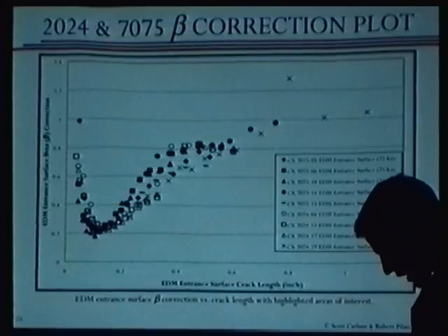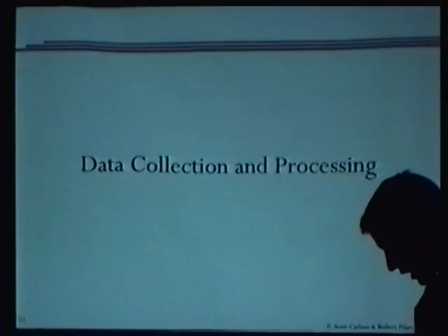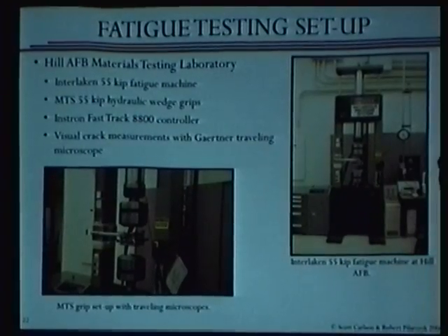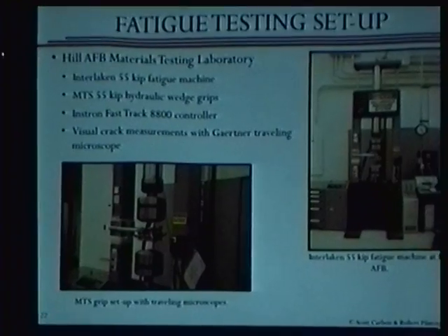But you take a microscope and you mount it to a machine. You see them right here. We built a little fixture, mirror rod, mounted them to this machine, and so they would traverse over the front and back, so both sides of that crack. And then on the back, in order to monitor the crack length through the bore, we would tilt it at a given angle, and then we would measure the bore length using it and calculate the angle at which we were doing it, and so, as my dad says, everything comes down to Pythagorean, so we would use the Pythagorean theorem, and we would figure out how long the crack was.